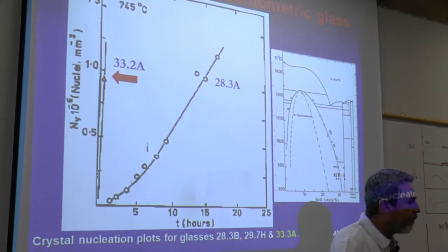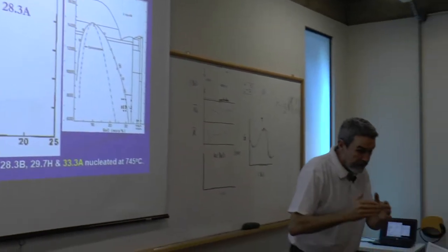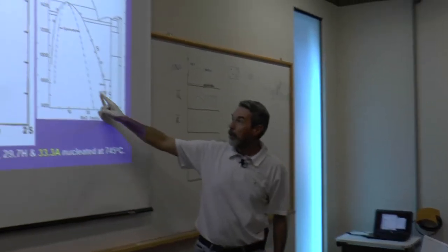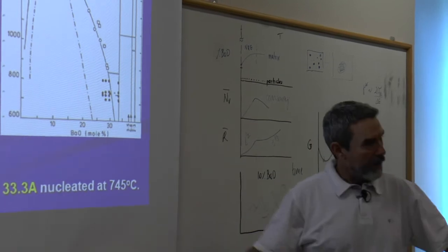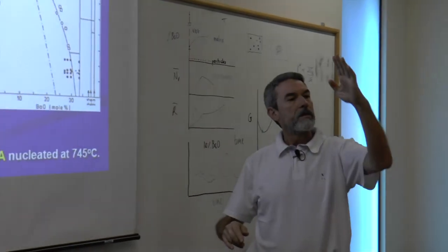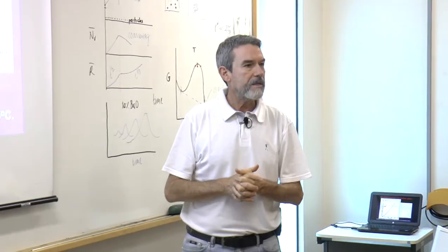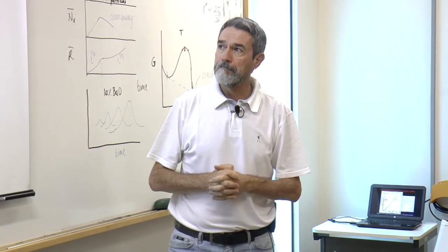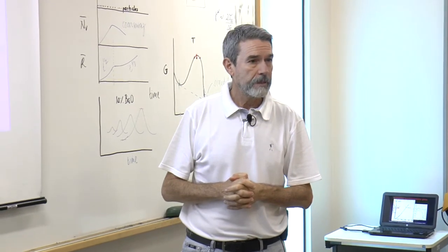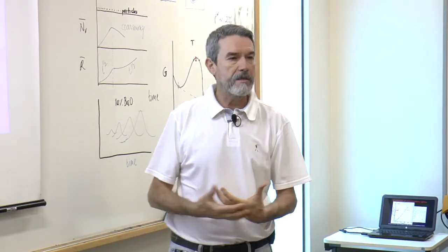It takes 7 hours to come from here to here. It takes 7 hours for the crystal nucleation rate to achieve its steady state condition. So what's the effect of phase separation?